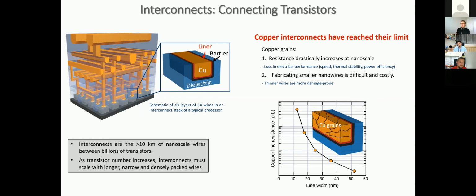And at some point, copper starts underperforming metals like tungsten and molybdenum. Those metals that you usually think of as high resistivity in the bulk start outperforming copper at this nanoscale, right? So there is a limit to how much you can shrink. You can scale copper down to a certain size, but at a certain point, you have to switch to better performing metals. It can be tungsten, molybdenum, even ruthenium, and so on. Those metals all outperform copper. Already at 10 nanometers, you see the issues happening in this resistivity plot.